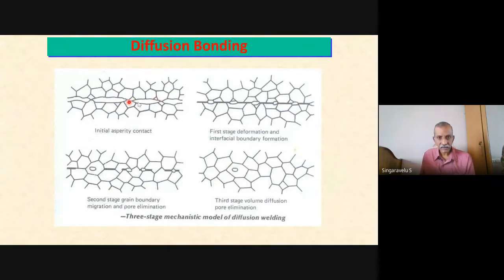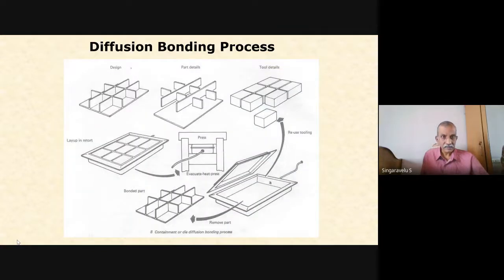Initially, we have some contact like that. The first stage is deformation and the interfacial boundary formation. In the secondary stage, there will be migration and the voids are getting eliminated. In the final stage, the entire volume of voids is eliminated, and you have the proper bonding between these two, right? This is one of the components by which we can do the diffusion bonding process. This is what the proper design. Okay, this is this component.